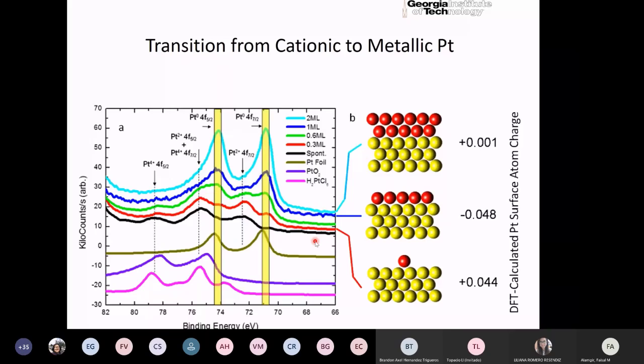But what if we have graphene as a cap? That is, graphene is the top layer, and it is put there intentionally to protect the platinum. In that case, first of all, we needed to see that we had a similar kind of effect where we could correlate the shift in our ORR potential to our platinum binding energy. And at the same time, we could see that compressive strain. So those two things are telling us that there is an epitaxial relationship between the graphene that you put on top and the platinum that it's interfaced with.